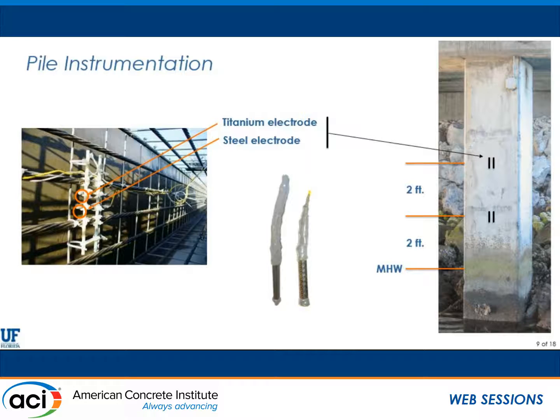The nice thing about this is that we can measure corrosion rates at the depth of the pre-stressing steel here because we know the area of the working electrode. And we have a nice titanium counter electrode so we can actually do straight corrosion rate measurements. We haven't done any of that yet because there's really nothing going on. All we've done is potential measurements. But we also have electrical connection with all the pre-stressing steel, and that's all tied together with the ties as well. So we have multiple ways that we can get to corrosion rates.